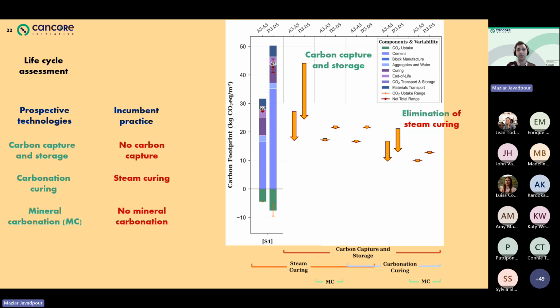So what are these two orange arrows, and what are these two minor trends representing? The first one is carbon capture and storage, which we expected. And the second one is the elimination of steam curing. So what is this actually telling us? This is telling us that doing carbonation curing and mineral carbonation in themselves, even though conceptually they should, in reality don't really contribute to lower emissions. So they don't really reduce our emissions, even though conceptually they should. The added energy and the added transportation reduce the benefits enough that we don't really see a meaningful reduction.